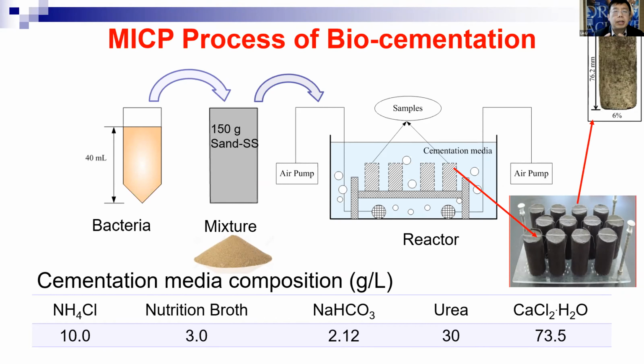Before we do that, we have to make the bacteria. The first step, we cultivate the bacteria and make them grow, making sure they reach 10 million in terms of the number of bacteria in the solution. Then we mix the bacteria with the sand and the steel slag. Once mixed, we put it in this, you can see, individually using geotextile. This geotextile is permeable to water but blocks the soil from moving out. So it is fully permeable and also maintains the shape, which is good to keep the soil in a cylinder shape.